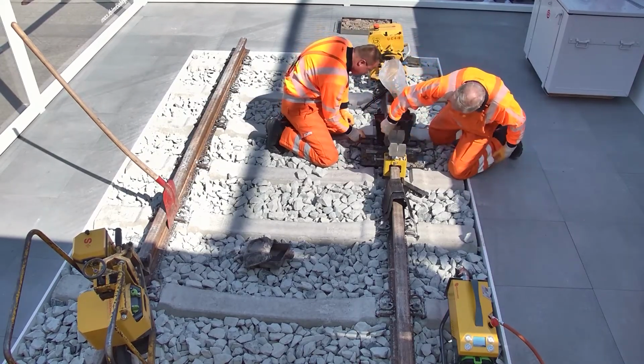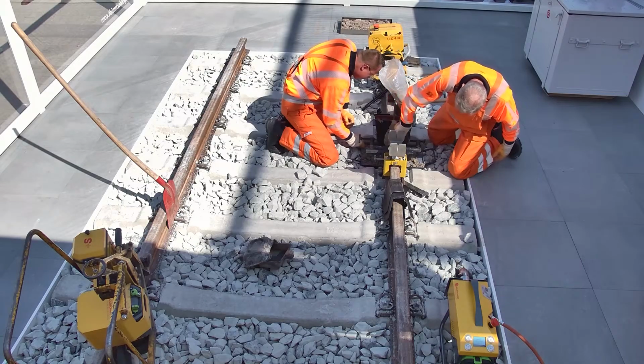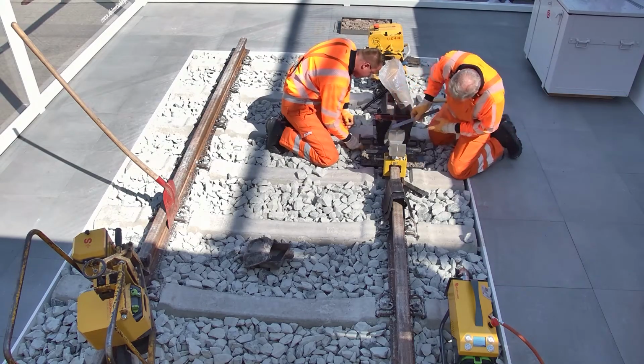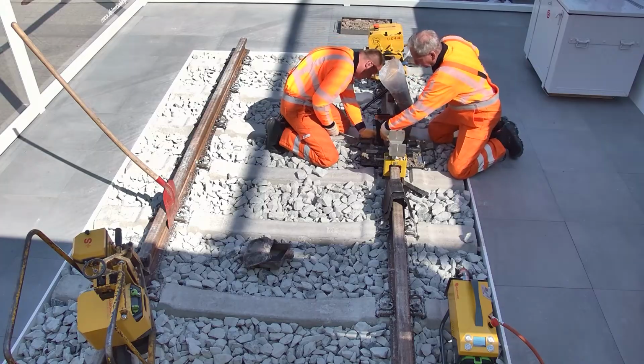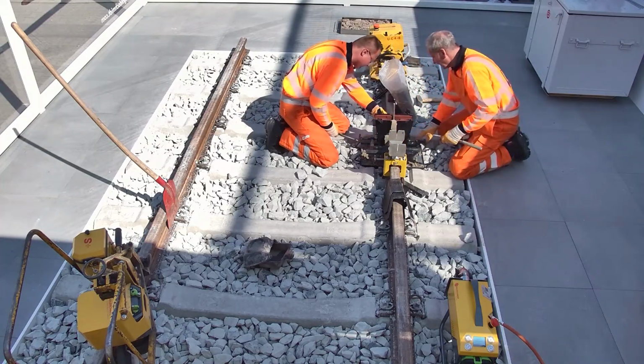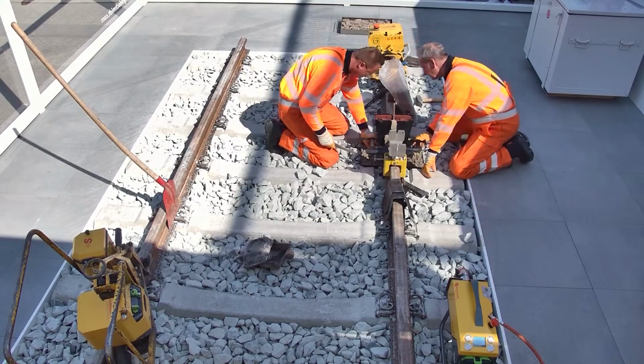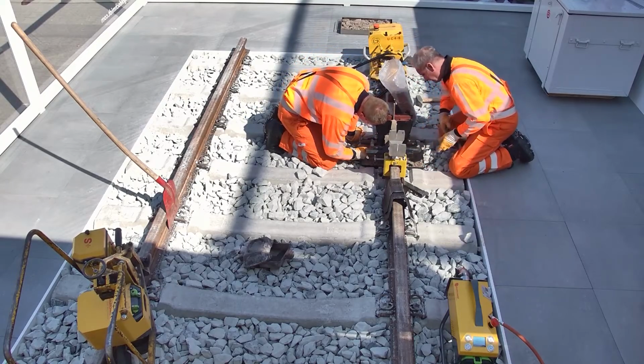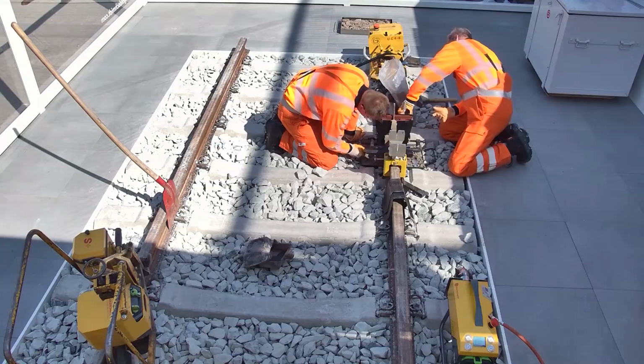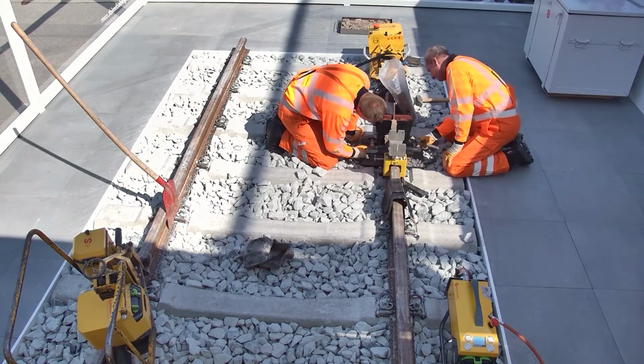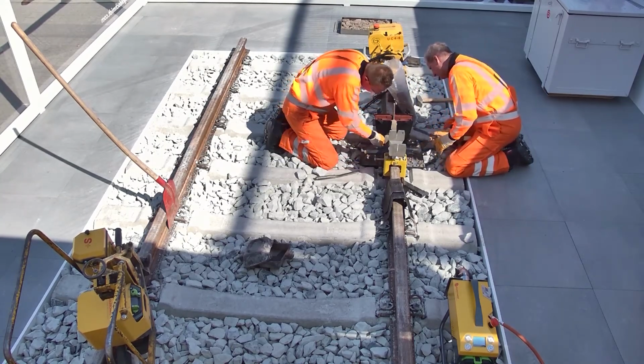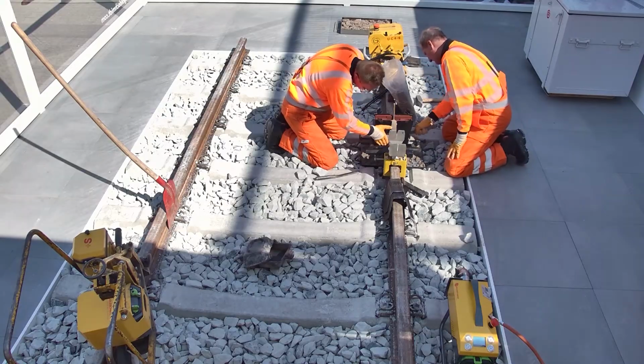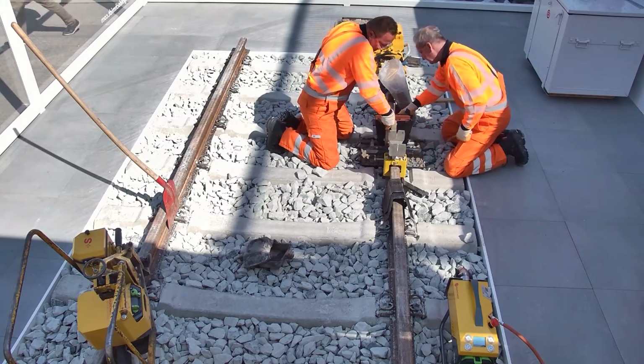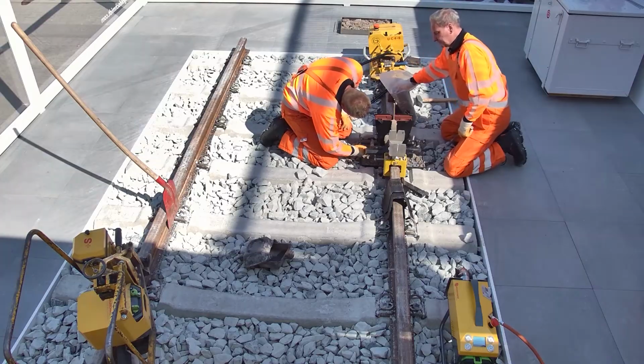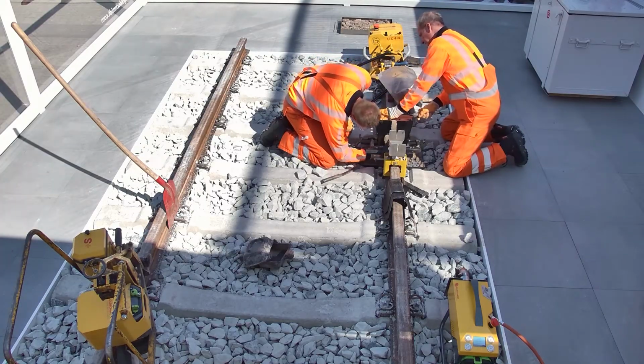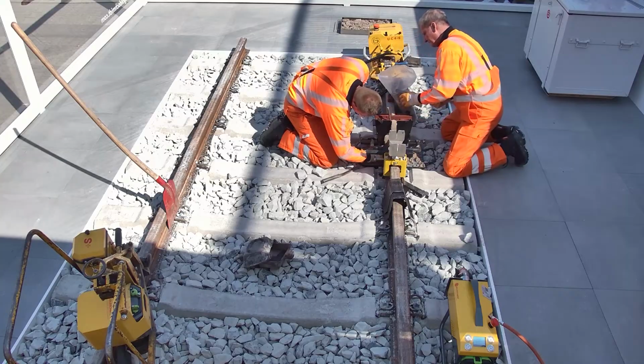Another reason to embrace luting sand as a sealing technology is the versatility. In very rare cases, we have new-on-new rail, but we have worn rail, we have different gaps, we have different sizes, and the luting sand accommodates any problem that we can see in the field. So any difference in gaps, any difference in rail profile, the luting sand will make sure that the liquid steel does not run out and the weld has to be redone.